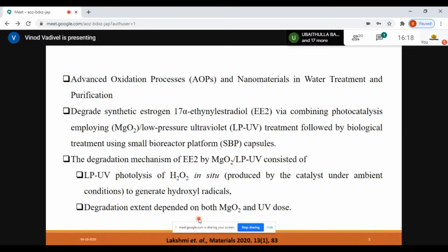And when you generate this hydrogen peroxide, you need UV photolysis to generate the hydroxyl radicals, and these hydroxyl radicals degrade your EE2 hormones. So it's like an advanced oxidation process with nanomaterials for water treatment and purification. The degradation kinetics depend on the loading efficiency of your magnesium peroxide and the UV dose. So when I spoke about this SBP, a small bioreactor platform,